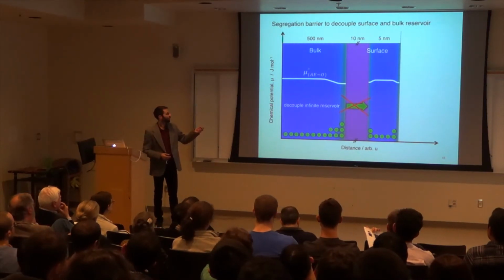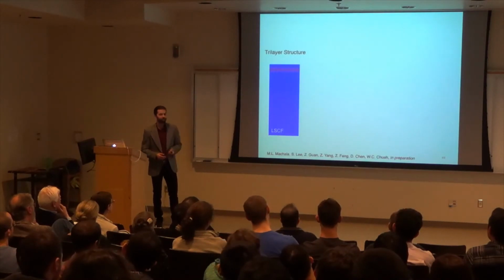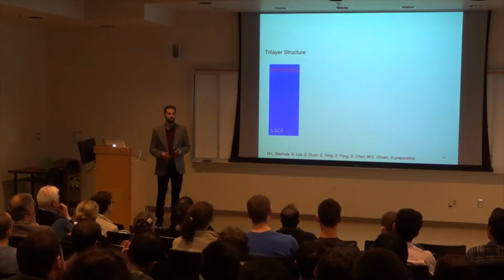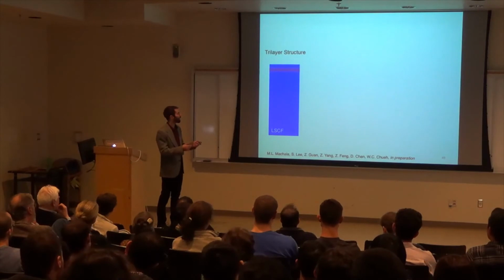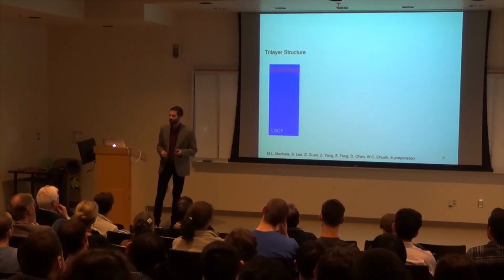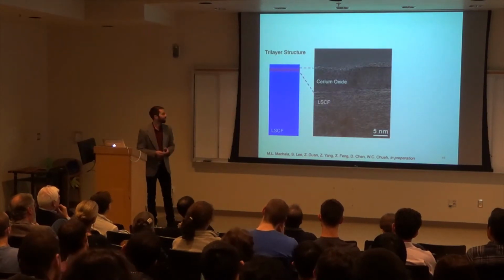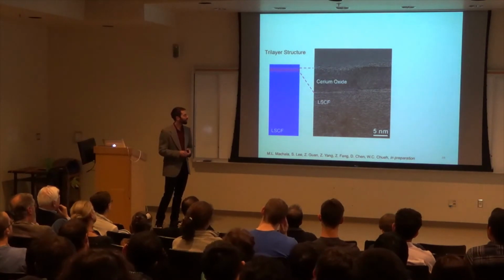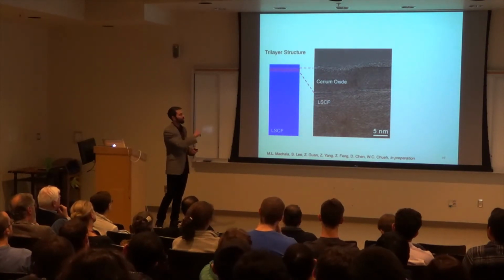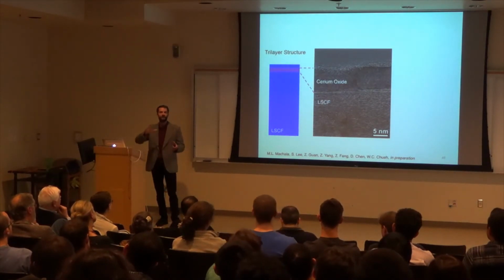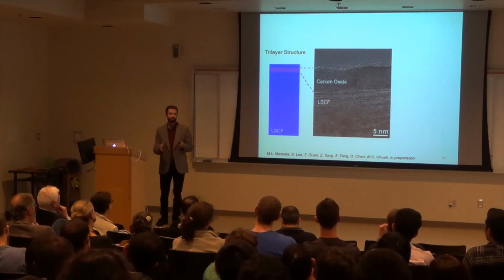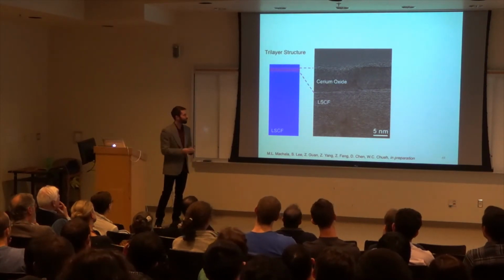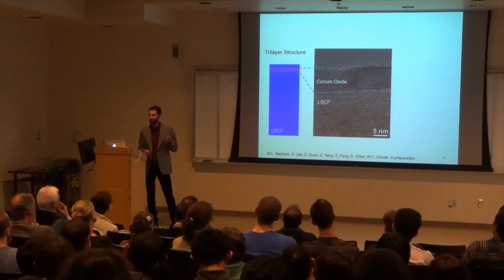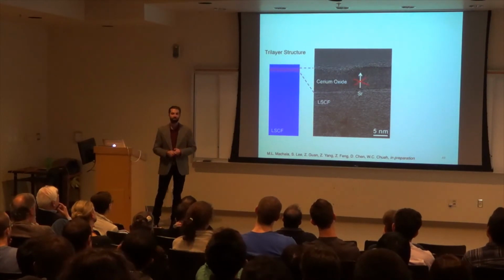So what I call this structure is a trilayer structure. And to understand what to put as this barrier layer, it must have certain characteristics. And what we show as our barrier layer initially is cerium oxide. Now cerium oxide is a fluorite structure, and it can grow epitaxially on top of this perovskite structure. Now, one of the things that we have to test first is, can it block strontium?